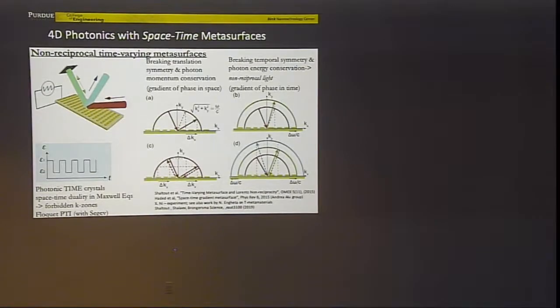So let's come back to these metasurfaces. As I pointed out, because of the additional momentum introduced by the metasurface, you break photon momentum conservation. As a result, a beam incident on this metasurface wouldn't be reflected in the direction dictated by the normal Fresnel law, but would go in some other direction depending on this delta K. That's because you introduce a gradient of phase in the space domain. But in this case, you don't break reciprocity. There is no reason to break reciprocity. There is the Lorentz theorem for this, which tells us that you have to have a magnetic field or nonlinearity or modulation in time to break reciprocity.